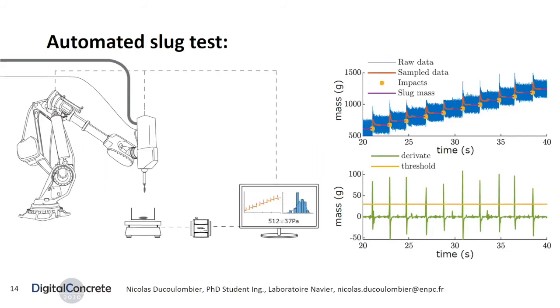A single collection gives us an estimation of the yield stress, while k successive measurements are necessary to estimate a confidence interval. However, in the context of digital fabrication, it is interesting to automate the test. A specific device has then been developed, connecting a balance load sensor to a computer via a standard acquisition card. A typical acquisition is illustrated on the right graph. The discontinuous flow results in a stepwise mass evolution through time, as shown on the orange curve on the top graph, where each step corresponds to a new slug.